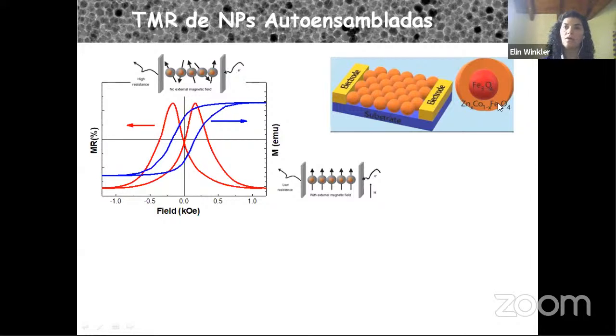That means the conduction depends on the polarization of the spins, and we encapsulate the magnetite with a semiconductor with very large resistance. Then we deposit the nanoparticles and we measure the conduction in this direction. So when we go from one nanoparticle to another nanoparticle, the tunnel barrier will be composed by the shell of the nanoparticle. And again, what do we expect?